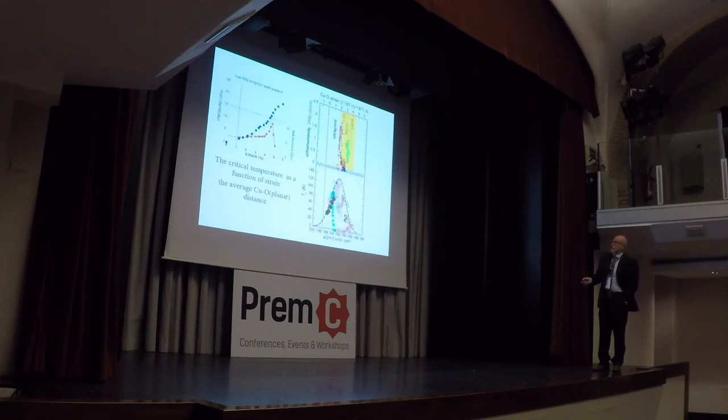The strain is very important in HTC superconductors. If you take the copper O2 plane, the copper O2 bond lengths, you have a strain field of the order of 1, 2, 3, 4, 5, 6%. And you have HTC superconductivity higher than 30 Kelvin only if the strain is 2.5%. And it's really a very fine control, in the meV range, of the chemical potential that controls the system. Quantum mechanics can emerge or not in our world.